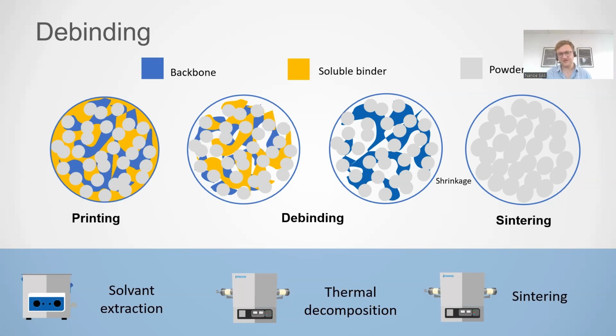At the end of that process, you should have almost removed all the soluble binder, but you still have what we call a backbone or a secondary binder, which is still there. And then you will take that part and put it in a furnace, and in the furnace, you are going to burn away the rest of the binder before sintering and to get a dense ceramic or metal.